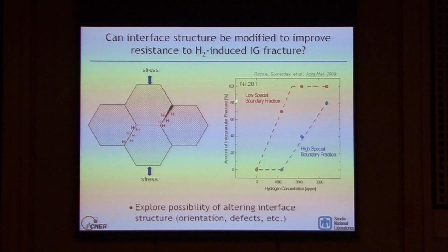What we're plotting on the y-axis is the fraction of intergranular fracture in these nickel alloys after they're exposed to hydrogen, versus the hydrogen concentration. Indeed, these boundaries that have more atomic registry have less intergranular fracture. So is there some other way we can try to manipulate just the intrinsic structure of grain boundaries in steels to mitigate the hydrogen-assisted intergranular fracture?